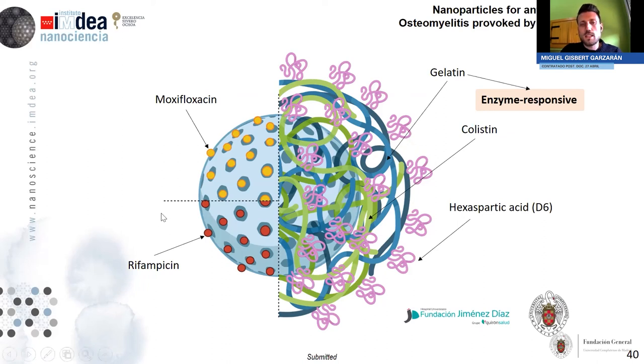So in this case, we designed two sets of nanoparticles, one of them being moxifloxacin and the other one being rifampicin. And then each of them was functionalized with a gelatin containing colistin, and then the whole layer was functionalized with an hexapeptide of aspartic acid because it presents affinity towards bone. So why gelatin? Well, because it can be degraded by enzymes, by different enzymes. And in particular, it can be degraded by the set of bacterial proteases that are secreted by Staphylococcus aureus.